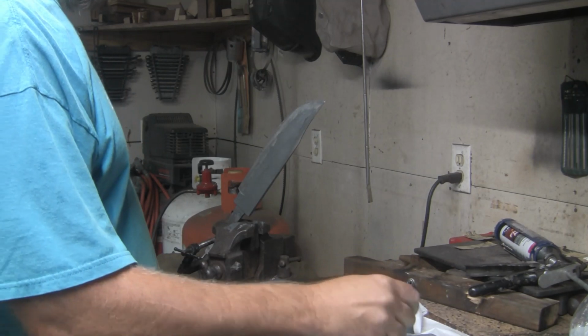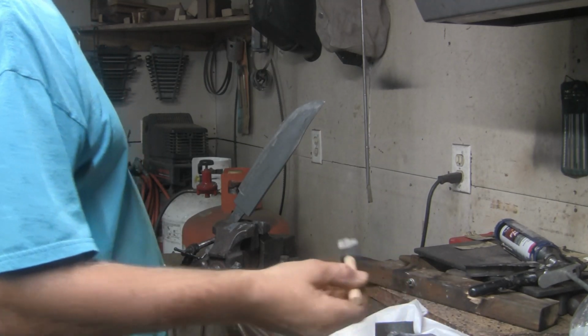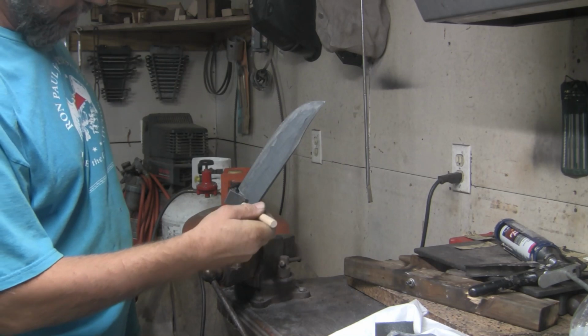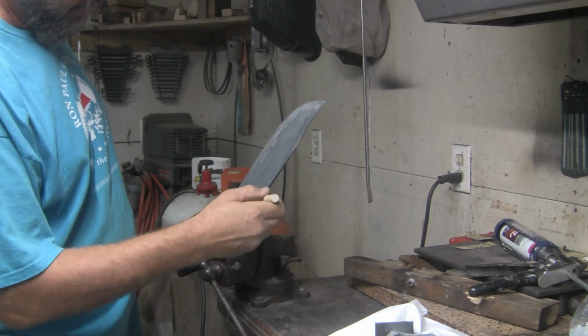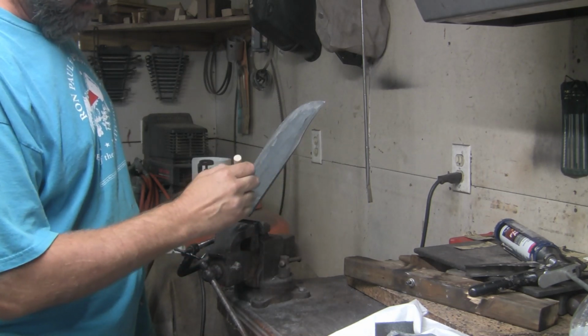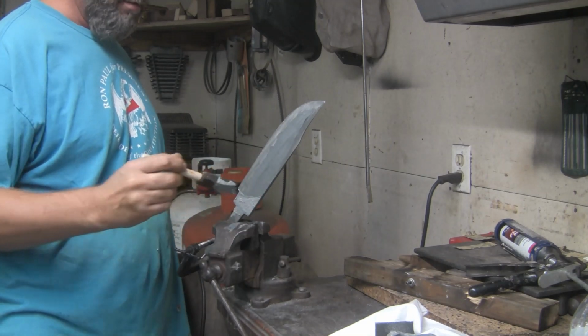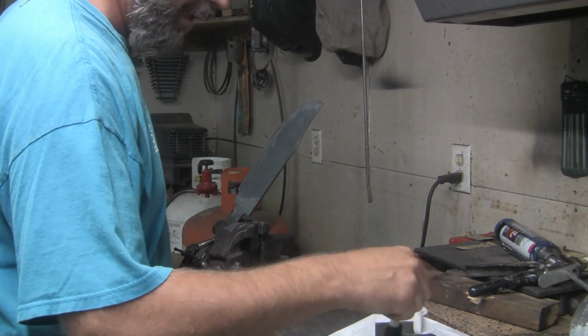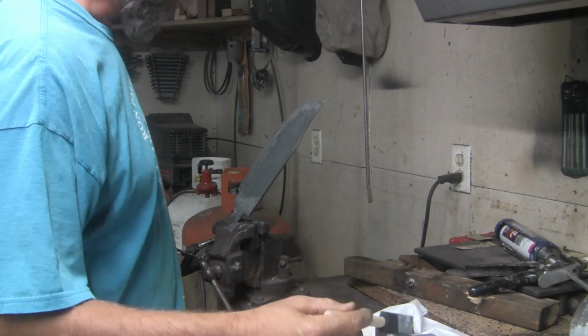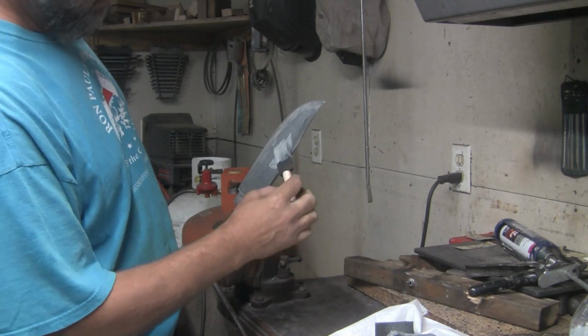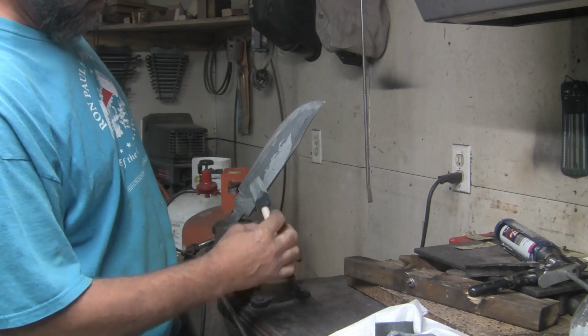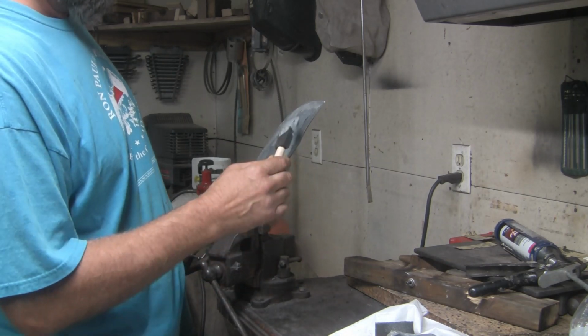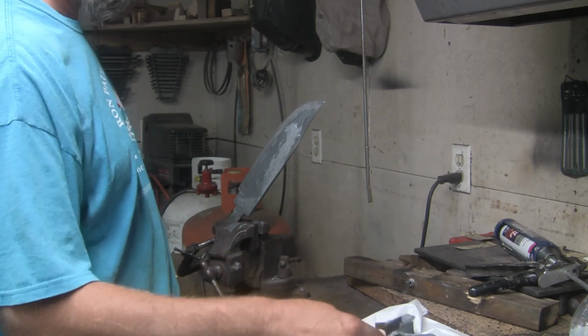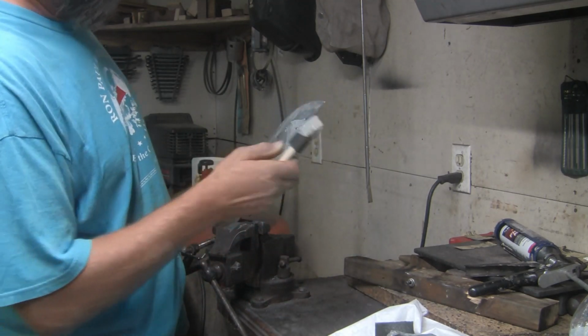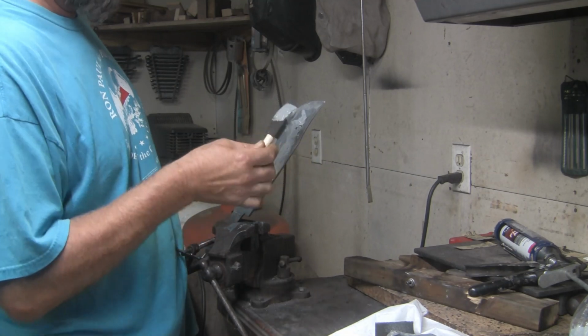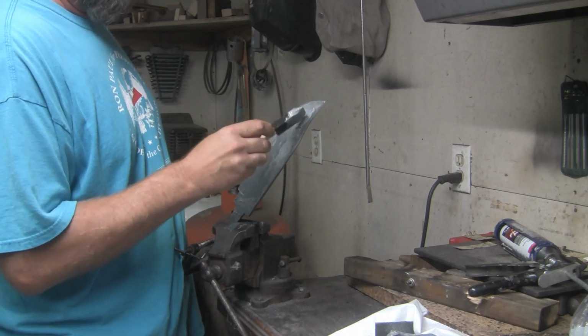Alright, so I'm going to apply a second coat of the thicker mix. And I did take this out and put it on my propane grill with one burner running on low, which kind of brought the temperature of the grill up to about 250 degrees. And that's just air temperature. It's not surface temperature of my metal here.